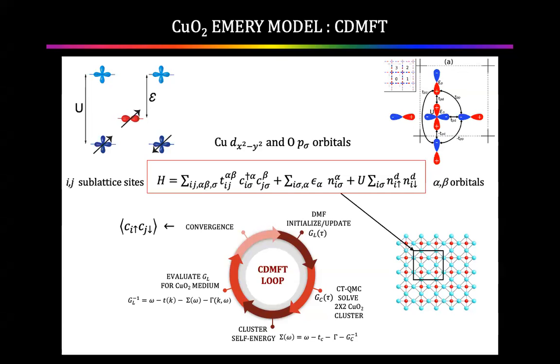Yeah. Just to get a few questions going. Of course, for charge transfer to work, you've implicitly made U infinite, very, very big. Yeah. So to say it's not there or to imply it's just charge transfer is to ignore the elephant that you've made infinite. If we examine the CDMFT, you're perfectly correct, but if we examine the CDMFT solutions and take them at face value, and the world leading CDMFT solutions are from Haule and Kotliar, so we do take them at face value, you don't have to increase the charge transfer energy very much before you kill the superconductivity. And the amount by which you have to increase it is tiny compared to the on-site.